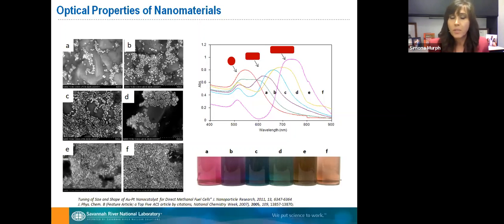So why is this important? For example, for a sensing application, whether you have a laser line that is 633 versus 785 is going to really affect the response of the interaction between the nanoparticle and the laser line. I will talk more about that. But also, depending on the length of these rods, you can have different colors. Even without any analysis or characterization tools, right away when you produce your rods or you have spherical nanoparticles, typically when we see pink and red, we are not that happy, because we know that everything is spherical, and we want other shapes.